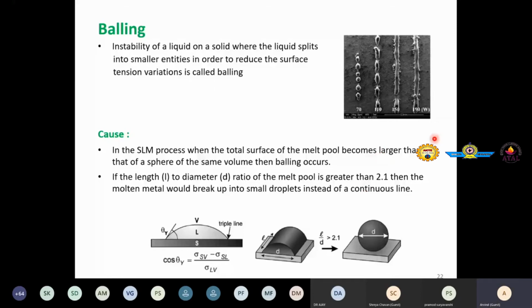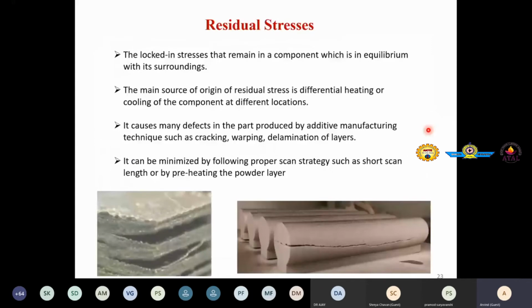I would like to elaborate on residual stresses. You see, residual stresses are defined as locked-in stresses that remain in a component which is in equilibrium with its surroundings. The main source of origin of residual stress is differential heating or differential cooling of the component at different locations. It causes many further defects like cracking, warpage, and delamination of layers.